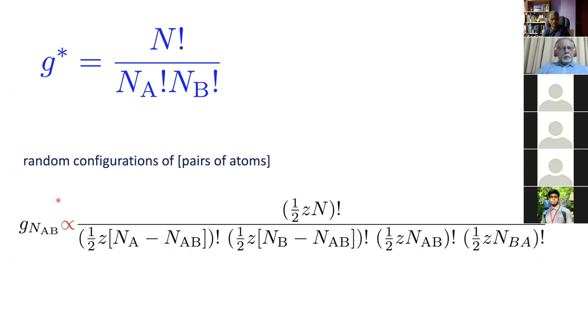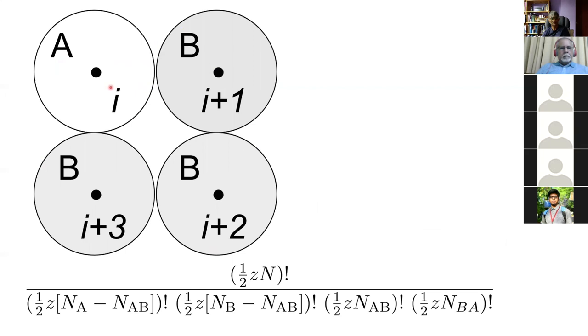An important point: while the analogous expression for a random solution is an equality, for pairs of atoms I've written it as a proportionality. This is because there's a fundamental problem when dealing with pairs: we can't count the number of AB bonds independently. For example, with four atoms A, B, B, and B: once you place B next to A to get an AB bond, and B next to B for a BB bond, the remaining BA bond is determined — it's not independent of the other bonds. So pairs cannot truly be treated as independent.